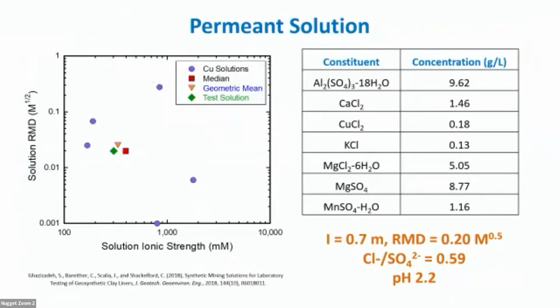The permeant solution we used, we looked in the literature for different copper heap leach solutions. There's a good paper out of the Colorado State group here on the geochemistry of these solutions. We picked a solution that kind of represented an average condition, shown over here with these constituents, is about 700 millimolar ionic strength.